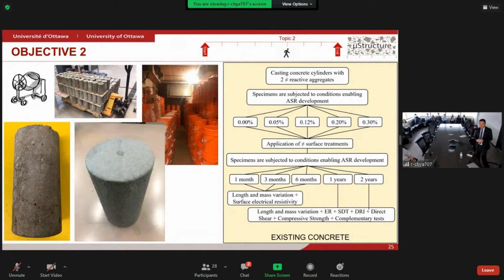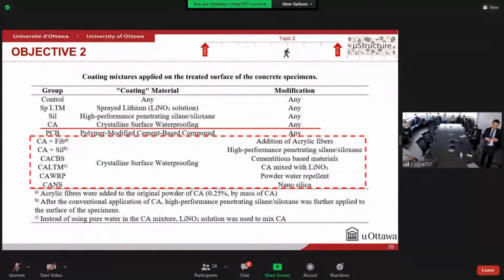We subject the specimens to develop ASR, and once they reach specific expansion amplitudes, we then treat the surface differently. After the treatments, we subject the specimens again to ASR development, and over time, we then evaluate mechanically and microscopically. So here is just a general overview of the different coating materials and different surface treatments we apply. I just would like to emphasize that we use crystalline surface waterproofing materials, which is the focus of this research, and we mix this material with different products such as fibers, high performance silanes, cementitious-based materials, lithium nitrate, water repellent,